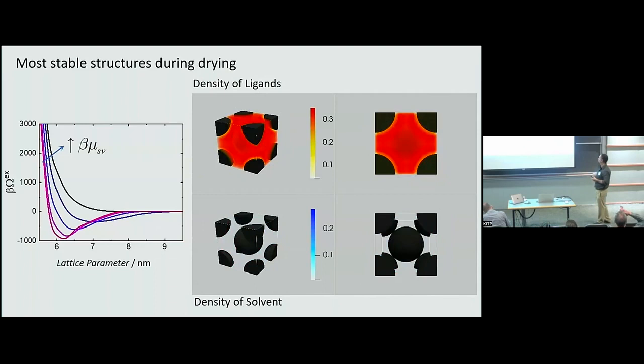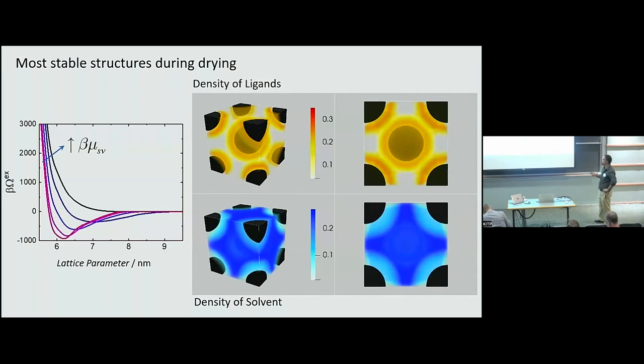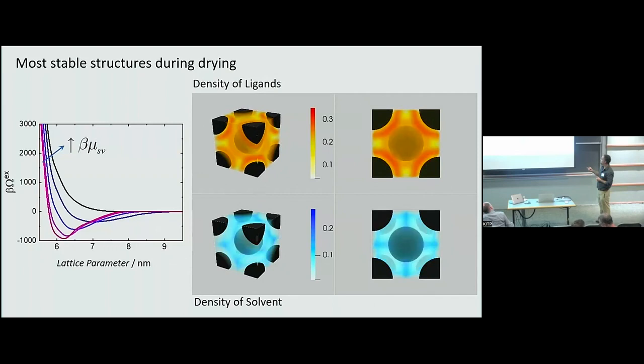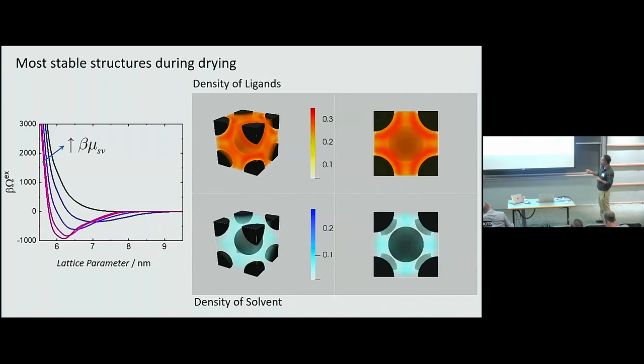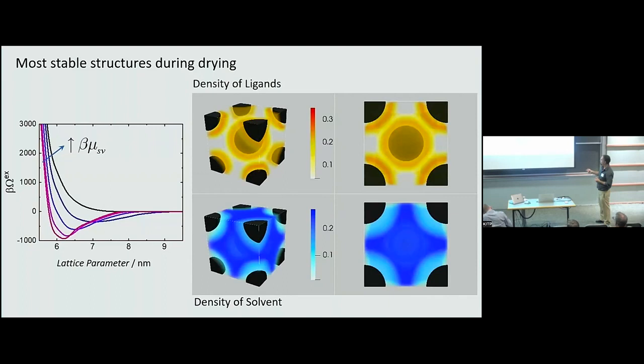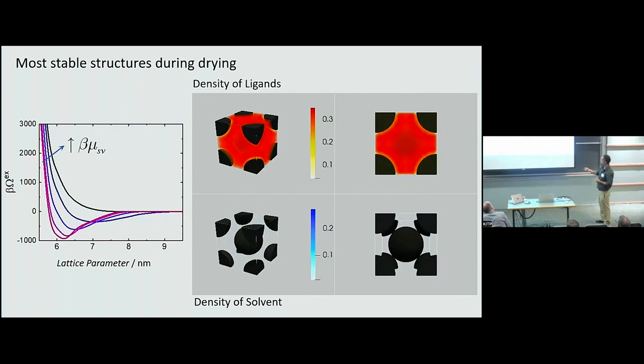And this is some structural information. Again, it's difficult to plot sometimes because you need to plot three-dimensional information, but this is the density of the ligand. You can see very well that each of these snapshots corresponds to one of the minimums on this plot. When the system is swollen, meaning this minimum around here for the black curve, you see very well the spherical symmetry of the ligand layer. And in these other plots, I'm showing you the density of the solvent. So there is solvent here, and then when it collapses, there is no solvent anymore.